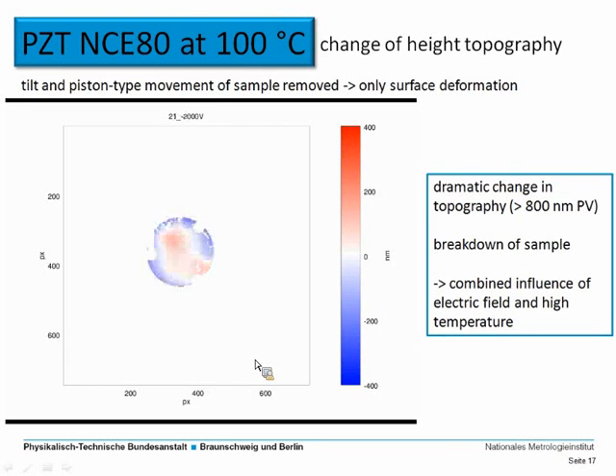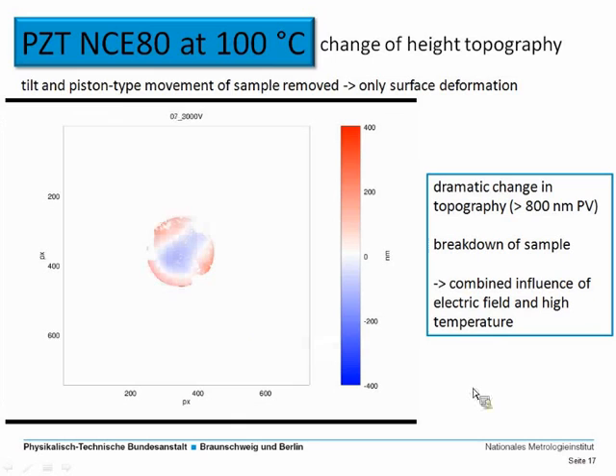Okay, now you can see at the negative polarities that somehow the surface shape changes dramatically. I'm also going to play this one again so that you can watch it again. And this breakdown that we can observe is probably caused by some combined influence of the electric field and of the high temperature. So this indicates that this is really almost the maximum temperature, or in this case, the maximum temperature for PZT, which was useful in this case.